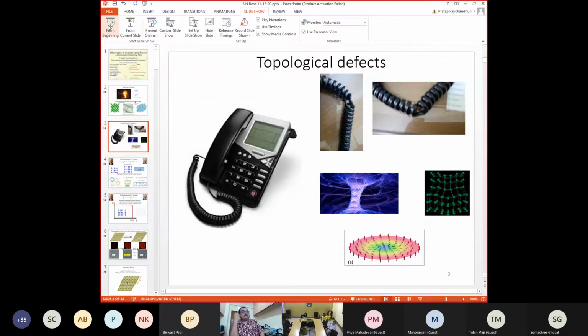All right, now what you can ask yourself, these kind of topological defects that you will also excite when you heat a solid, can they induce melting? This is the problem which in the 70s, these two gentlemen, David Thouless and his postdoc Kosterlitz, started working on. And they took a very simple model, which is called the XY model. In the XY model you have spins, and the spins can only point in the XY direction, XY referring to the plane. So they have no component out of plane, which is the Z direction. And then you have a ferromagnetic coupling between them. So it is the usual minus J Si dot Sj, and you can write it as cos(theta_i minus theta_j) by defining the angle of this spin with some general reference axis.